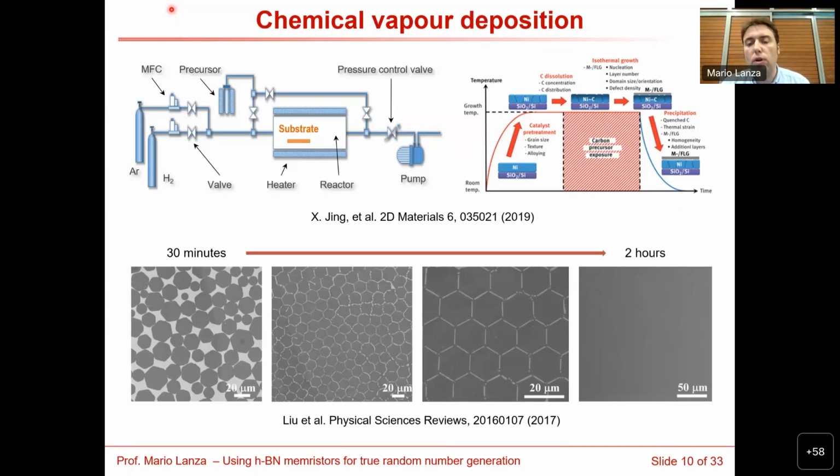After that, growing more material on the first layer, the speed is reduced. So if the environment is clean, and this is why you have the pumps, in principle, you may see thickness increase, maybe some multilayer islands if you have some local defects in the first layer.